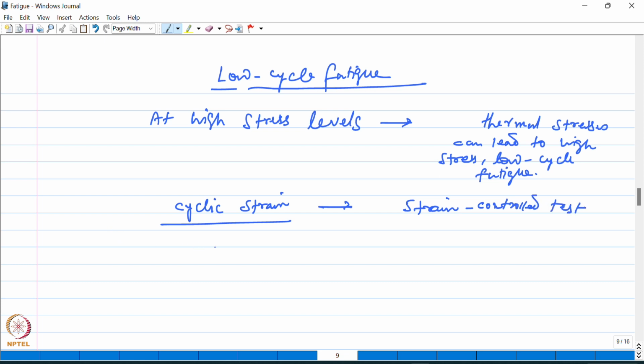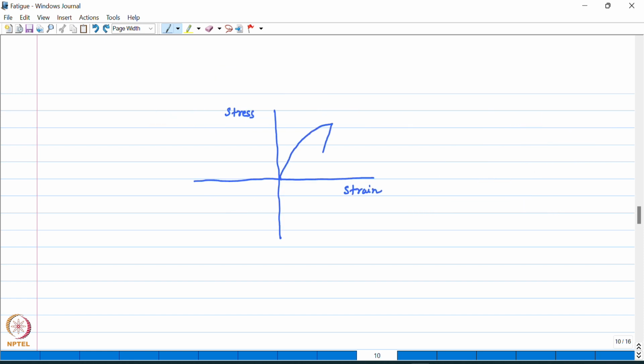And if you look at the stress strain curve generated under such conditions, when the strain amplitude is held constant, it will look like this. So here OA is loading in the positive direction, or in tension. Now if it is unloaded and reloaded in the opposite direction, that is in compression, then yielding will occur at a lower stress, which is the point B over here.